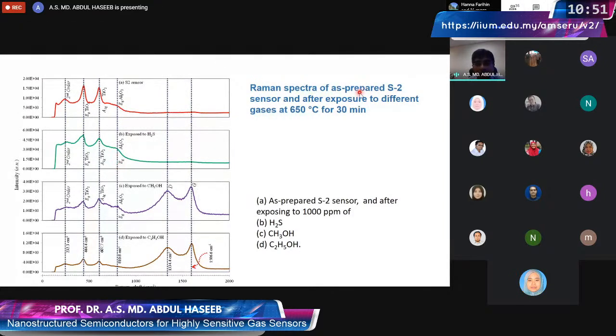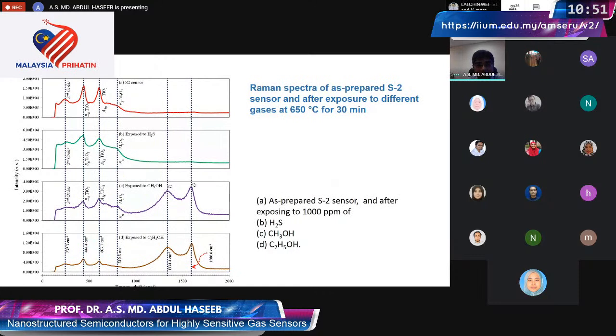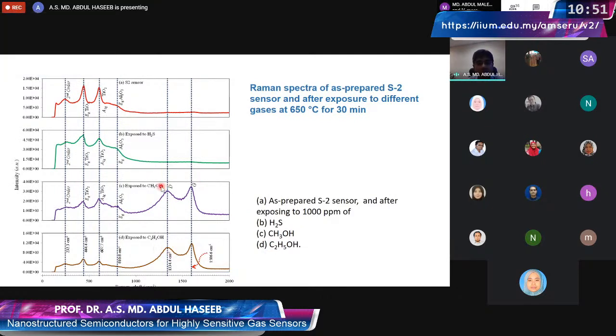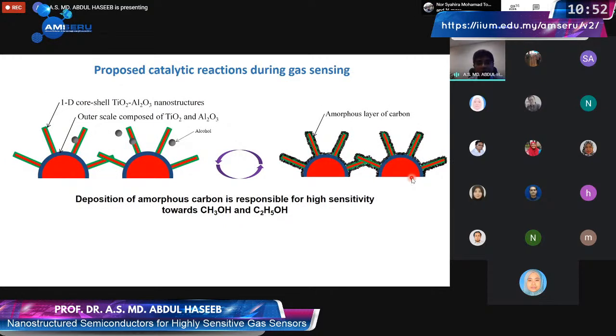And when we do the Raman spectra, we particularly notice one thing. In the case of the material which was exposed to alcohols, we see a deposit of amorphous carbon, which is not present in the original material, and which is not present in the material exposed to hydrogen sulfide. So that signals to us that things are happening there. And of course, we remember that in the presence of this alcohol, the sensitivity is really very high.